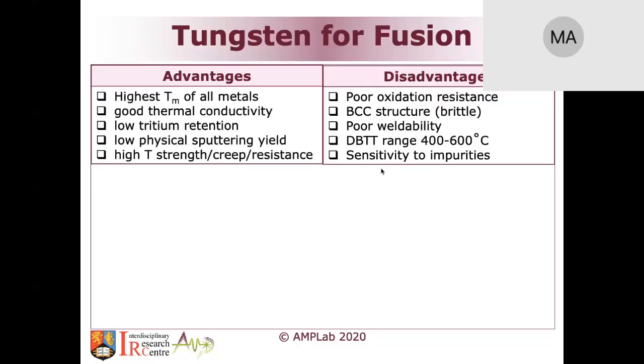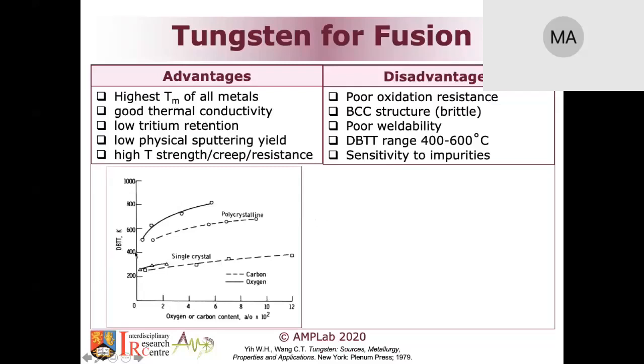I found some references that look into that, and they all go back to the 1960s and 70s from early work from NASA. So for instance, you look here into the first one, ductile-to-brittle transition temperature. And you can see that additions of oxygen or carbon will increase the ductile-to-brittle transition temperature, which is bad news, because in additive manufacturing, we are handling powders in oxygen, most likely. Even if you're using argon in a powder bed machine, you still have some oxygen, you have a very large surface area. So you're likely to increase the ductile-to-brittle transition temperature in a polycrystalline tungsten, these two lines there. And that accordingly will get the material to be in a brittle fashion below those temperatures.